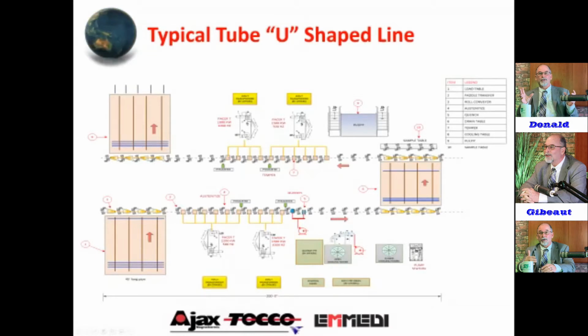You see the quench pit, open tower down here. We do closed towers there as well. Closed cooling system for the more high purity water, because as this hot pipe comes out, here it's quenched out, but all the way through this austenitizer, it's getting hotter and hotter. So you've got to water cool the rolls. Same thing all the way through this temper and all the way out, you've got to water cool your rolls. All that's put on this closed tower here.